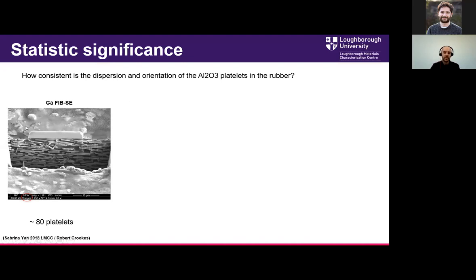So here we have a gallium FIB cross section of some aluminium oxide platelets in rubber, and this was trying to recreate a nacre structure. We wanted to know what the dispersion and orientation was and what sort of defects were there. And you can see with the FIB cross section that we take in a sensible time period, maybe an hour or so, we can only see an area of 80 platelets. So we don't really have any statistical significance from this.